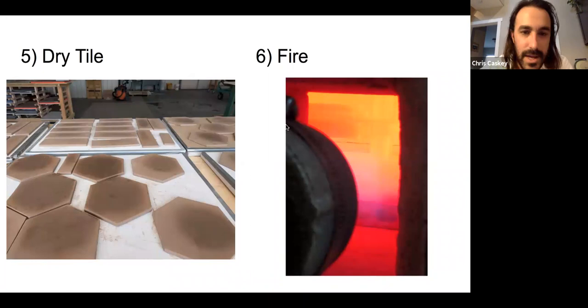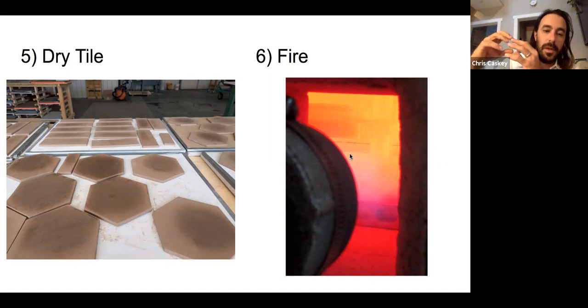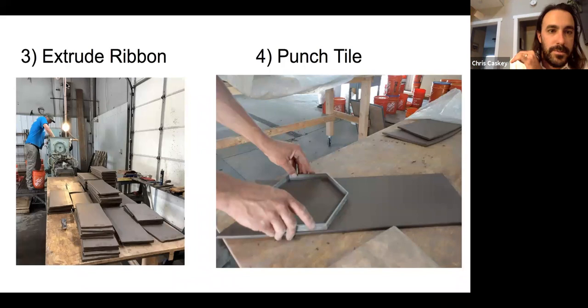The goal is getting to a high enough temperature where stuff is just going to fuse together. And when I say stuff, I mean the clay particles. They're going to very slightly melt on the surface and have fusion between adjacent particles. So going back to this extruder here, this pipe is pumping air out of the clay so that we have less air in the clay, which means we have more nearest neighbors between our clay particles, which means we can have a stronger fused network when they all melt together.